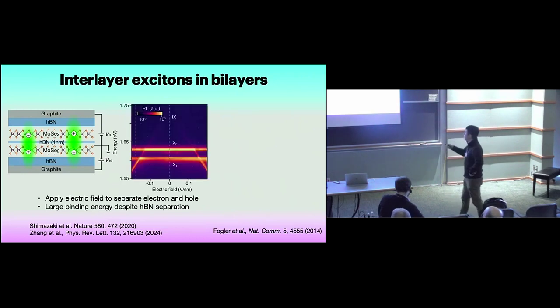When you do so, here I'm showing the photoluminescence of the sample as I vary the electric field. You see that there is a nice Stark shift because the interlayer exciton has a permanent dipole, but the intralayer exciton does not show any Stark shift because of the 0 dipole moment out of plane. What's pretty nice about this system is that the interlayer exciton photoluminescence intensity is actually quite comparable to the neutral exciton. So we can get very bright interlayer emission from such systems.